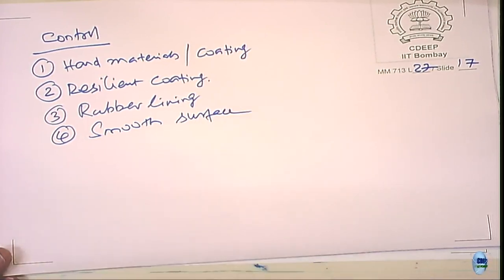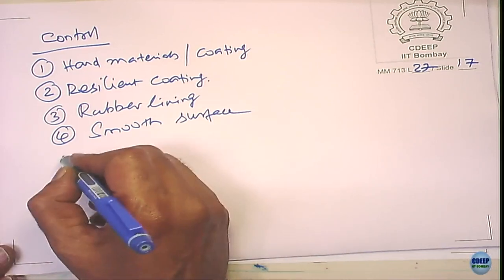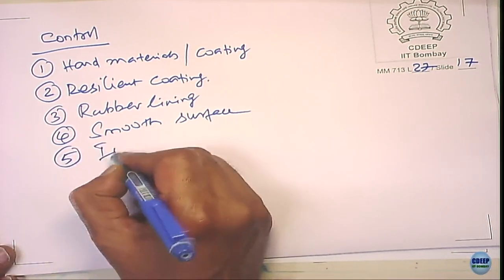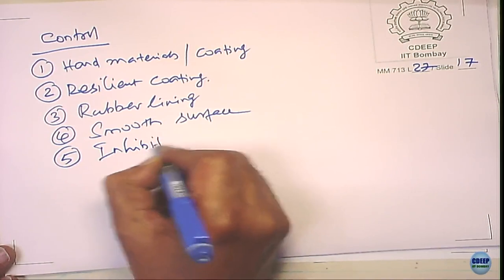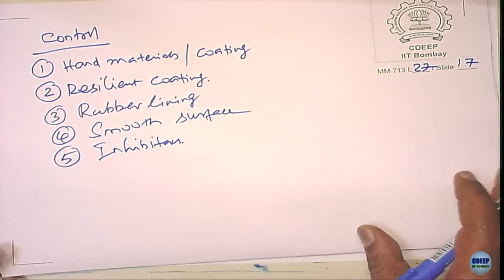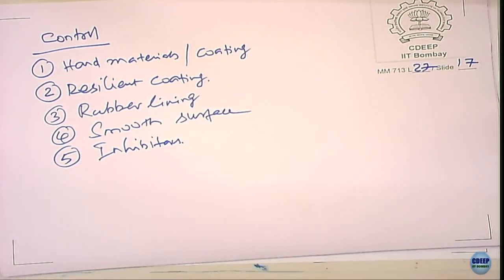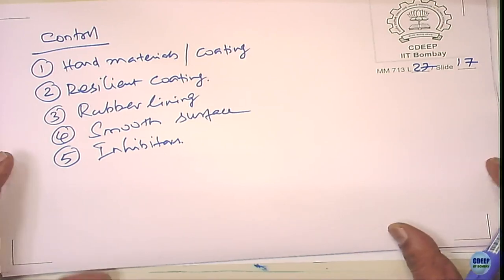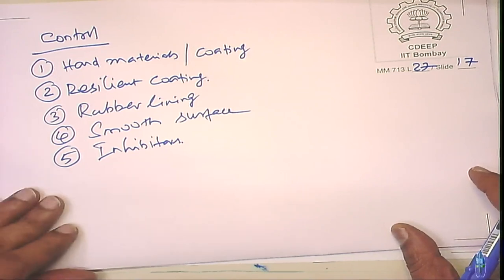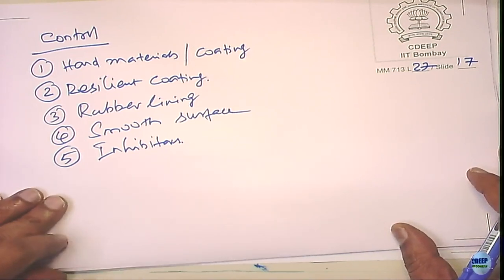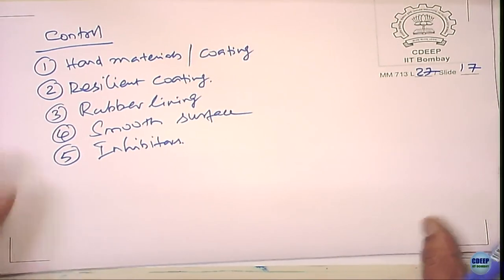What is the advantage of a smooth surface? It doesn't allow the bubble to stick on the surface. Can use inhibitors. The fact that inhibitors reduce cavitation damage means there is a corrosion taking place, simply not a mechanical damage per se. Okay, so that should come to the end of the discussion, unless you have any questions.